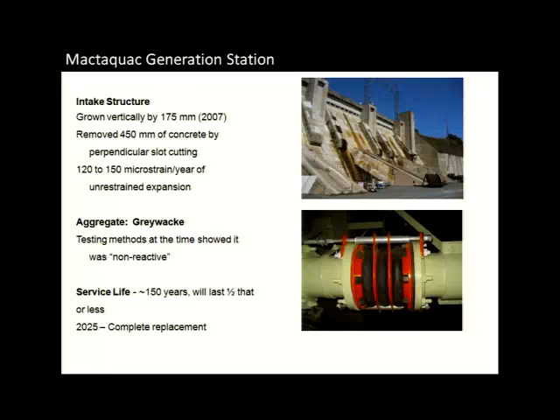So they had all the propensity set up to have ASR going on in this structure. They started to notice cracking, and started doing monitoring about 10 to 15 years after the structure was built. What you see here is that because the structure is embedded in bedrock on either side, the only place it can go from this expansion is up. It has grown by about 175 millimeters since it was built, about 7 inches of growth in a structure like this.